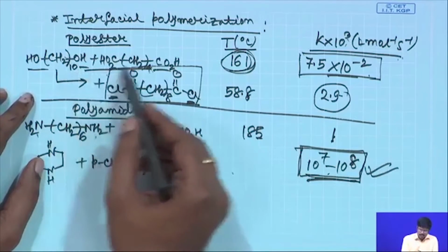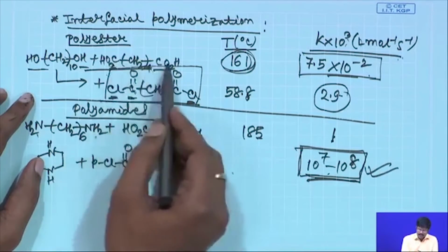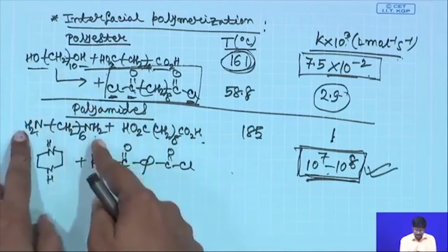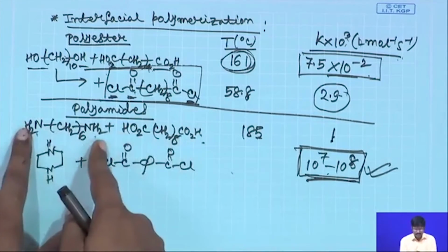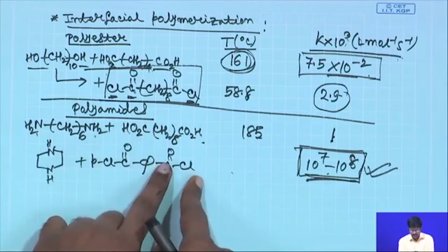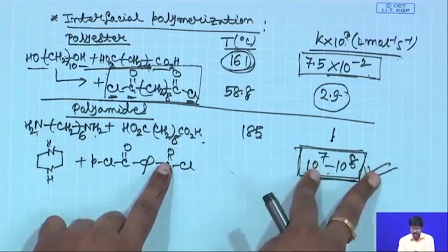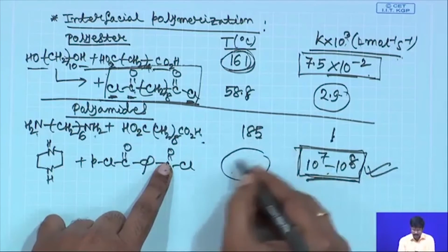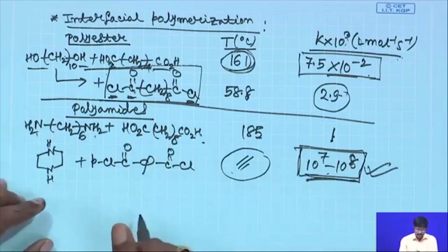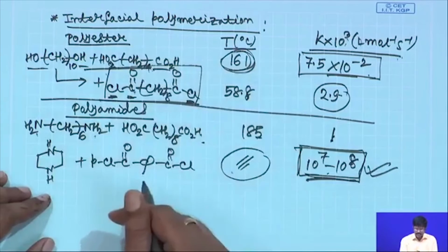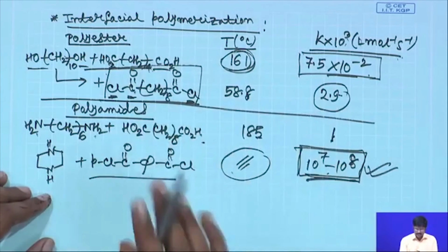However, if the dicarboxylic acid, say you are reacting dicarboxylic acid with a diol or a dicarboxylic acid with a diamine, if you can activate the dicarboxylic acid by using an acid chloride, then the reaction rate goes up manifold, rate constant goes up manifold. Although the data is not there for the temperature here, you will see that many of these reactions can be done between 30-40 degrees Celsius, even close to 0 degrees Celsius. So, that is the effect.